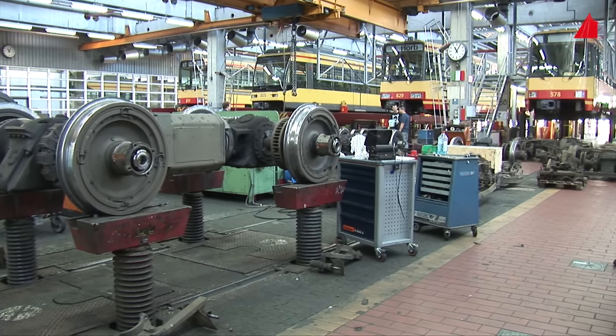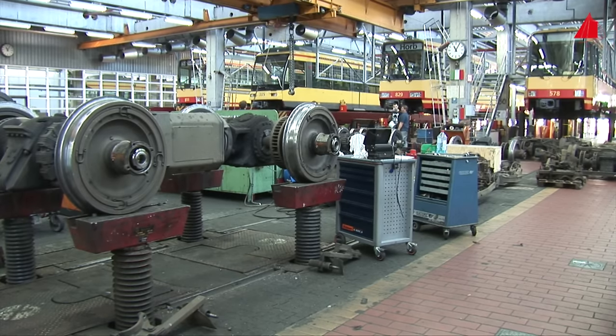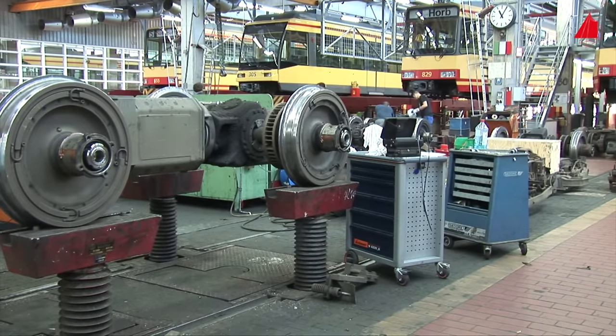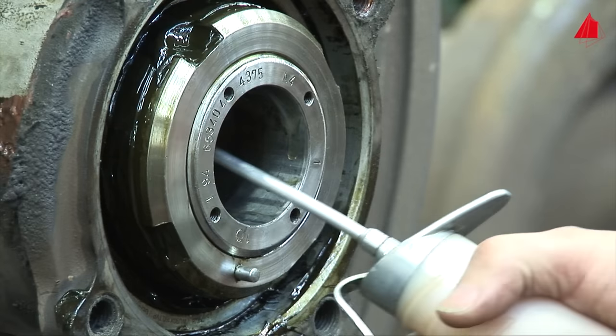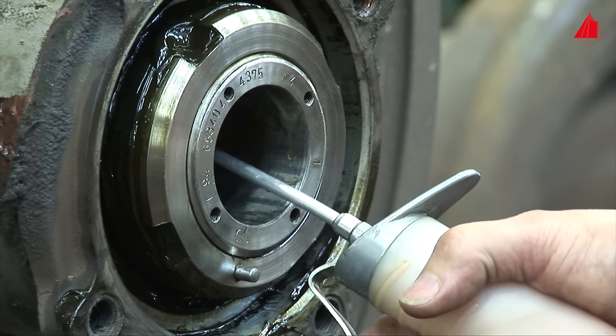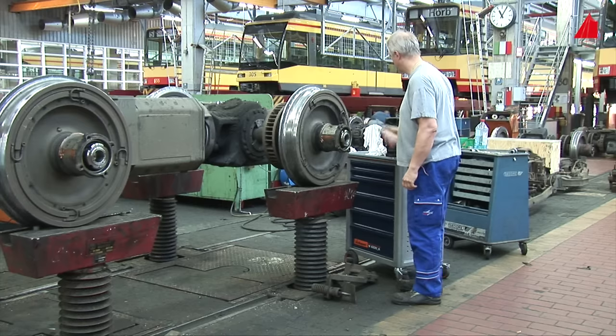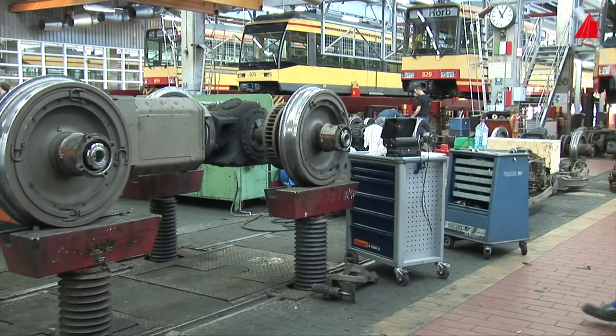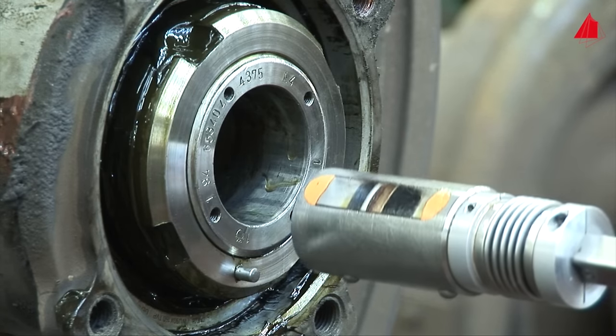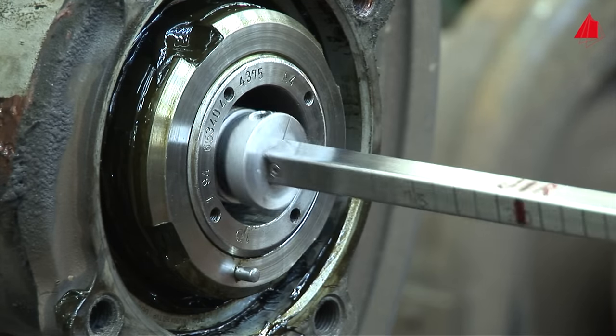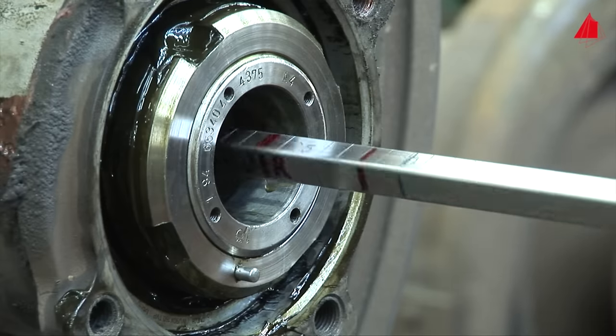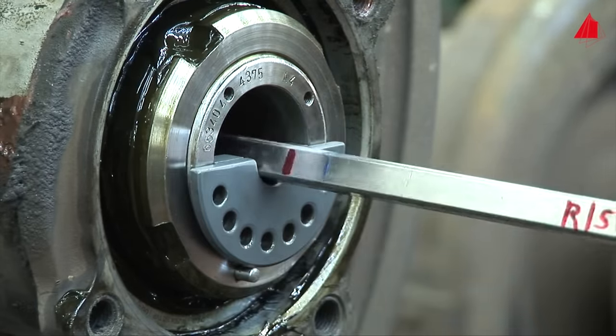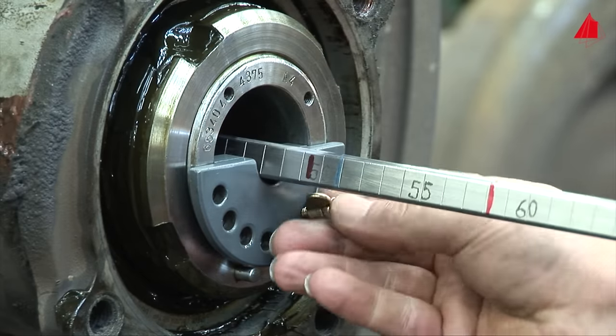Special attention is given to the wheel axle, among experts known as wheel set axle. It has been designed as a hollow axle—this saves weight and facilitates the ultrasonic examination. The material tester applies a suitable oil as a couplant into the bore of the axle. Now he takes a special probe designed exactly for this purpose, inserts it carefully into the bore with the mount, and evenly spreads out the couplant by turning and pushing. He has accurately marked the most important examination points at the mount.